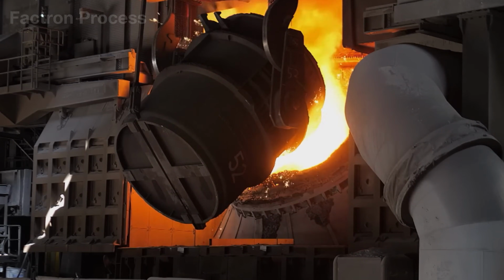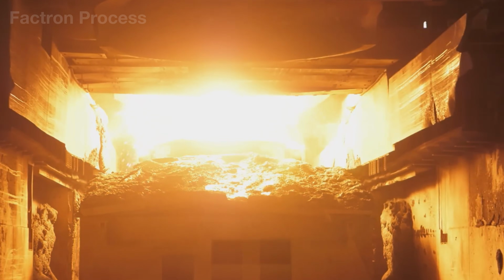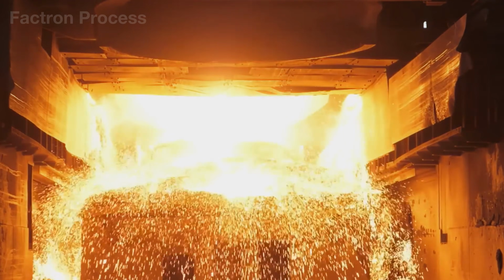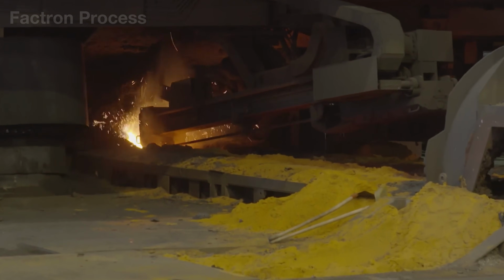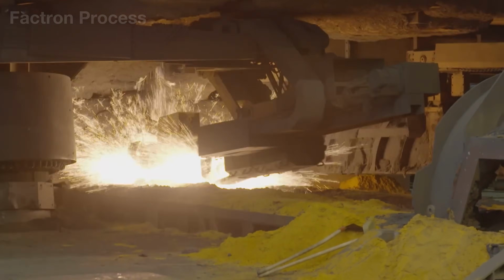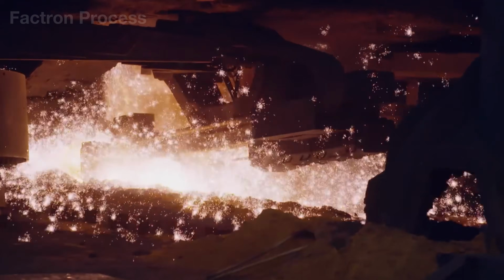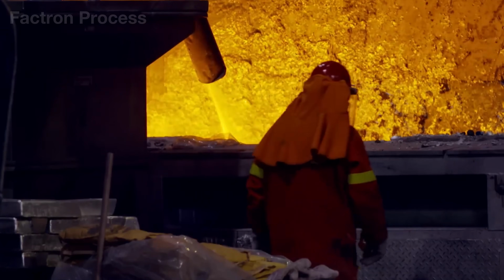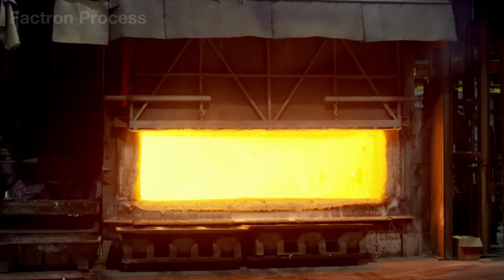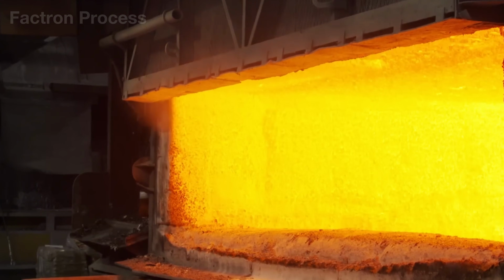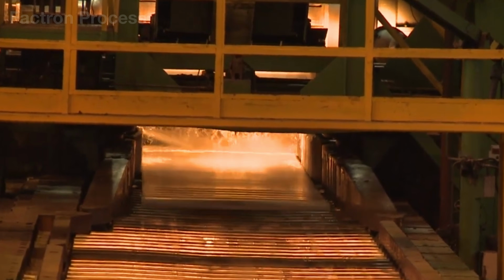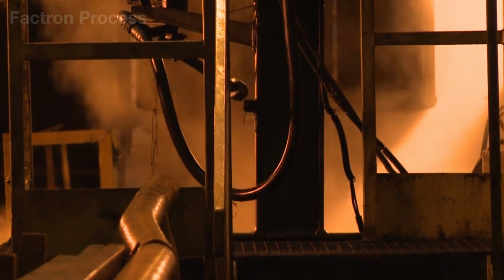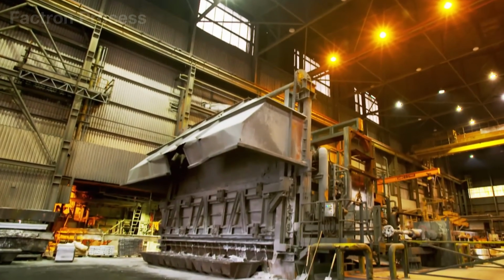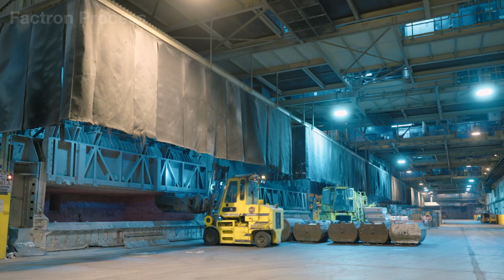Although the aluminum has already become a glowing pool of molten metal, it is not yet allowed to proceed directly to the casting area. A technician takes a small sample from the furnace, cools it, and analyzes its composition, because can bodies and can ends contain different proportions of alloying elements. Based on the results, pure aluminum and the appropriate amount of manganese or magnesium are added to the molten bath. The stirring system immediately creates circulating currents that blend the added elements evenly throughout tens of tons of liquid metal. Only after the bath reaches the required uniformity and cleanliness is the aluminum transferred to a holding furnace, where it waits to be poured into the casting pit and transformed into slab ingots weighing tens of tons.